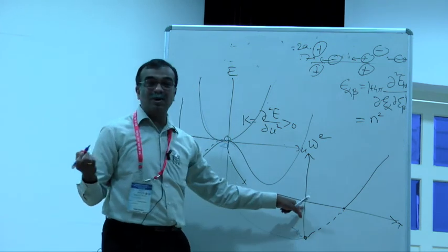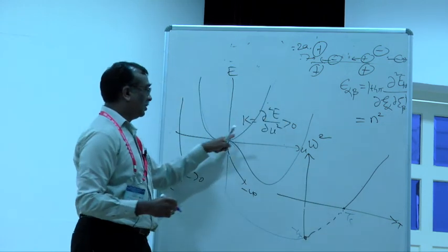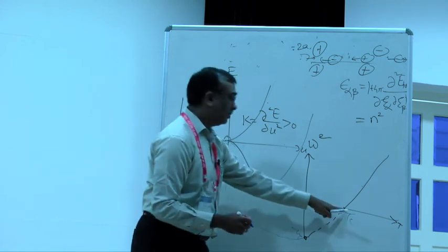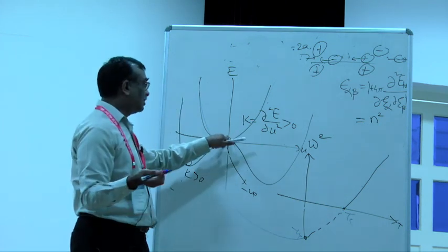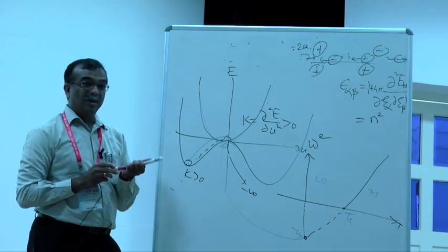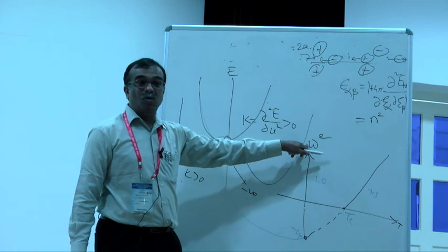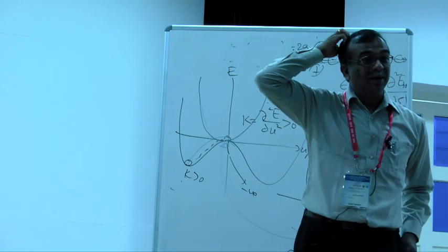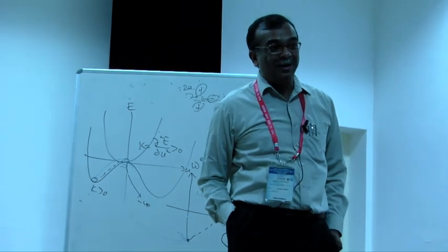So at 0 Kelvin, you will not have that structure stable. But up to some temperature TC, this high temperature structure can be stable due to vibrational free energy. So thermal vibrational free energy stabilizes the high symmetry structure above this. This is the high symmetry structure. This is the low symmetry structure. Low symmetry means the atom is off-centered from the high symmetry structure. So this is what is meant by omega squared being negative in your DFT calculation. That means your structure is unstable. Now your question is, if you change k points, you get what? That question I didn't understand. That sounds like a numerical issue.